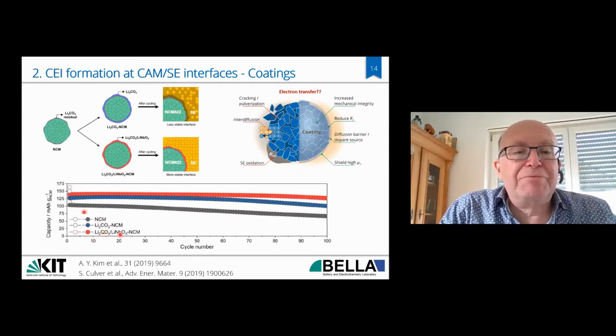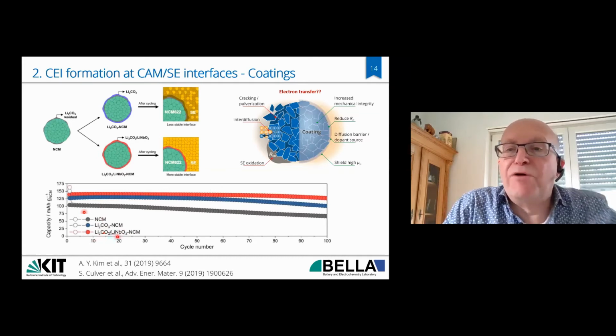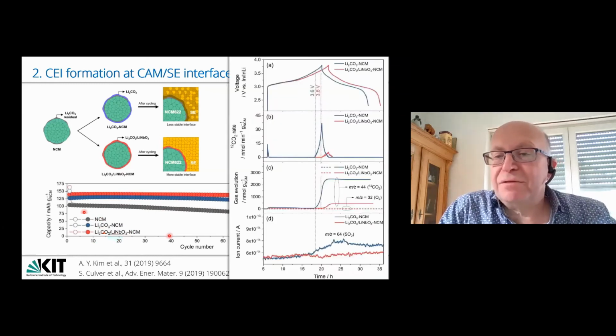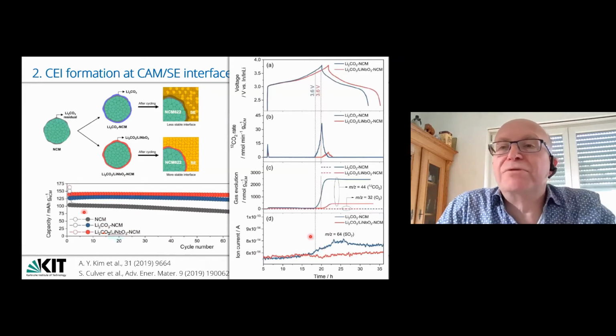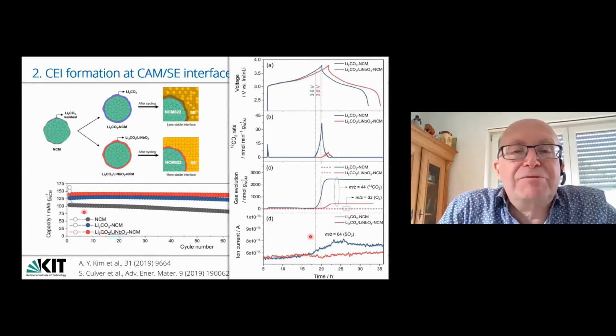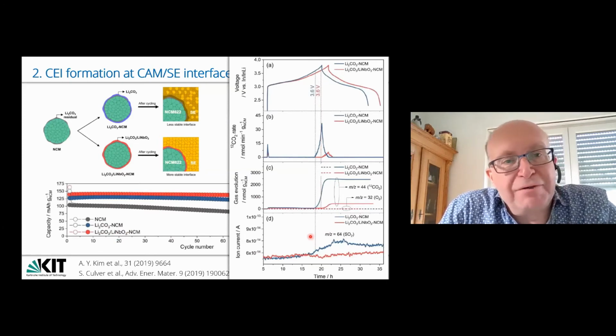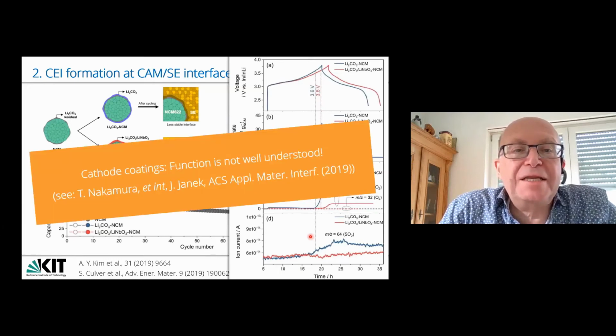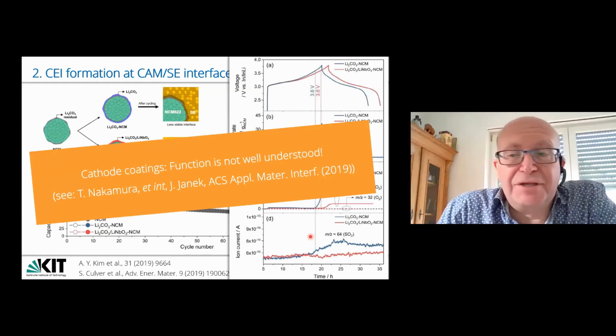This is the red data when we used our mixed lithium carbonate, lithium niobate amorphous coating. If we have this amorphous coating, you see that even then, so this is the red data here in the DEMS data, there is no SO2 being shown. So in fact, the coating also seemed to really solve that issue of direct reaction between the NCM material and the electrolyte, but not completely. You see there's still fading, and I think there's still work to be done. And I think I also have to conclude that cathode coatings as such are not so well understood. So there is still room for work on cathode electrolytes.